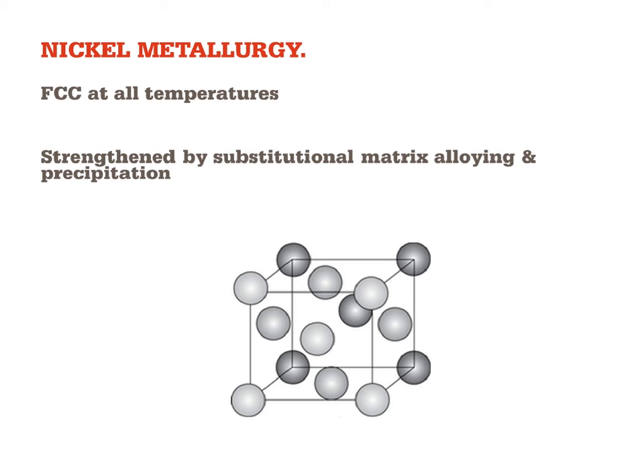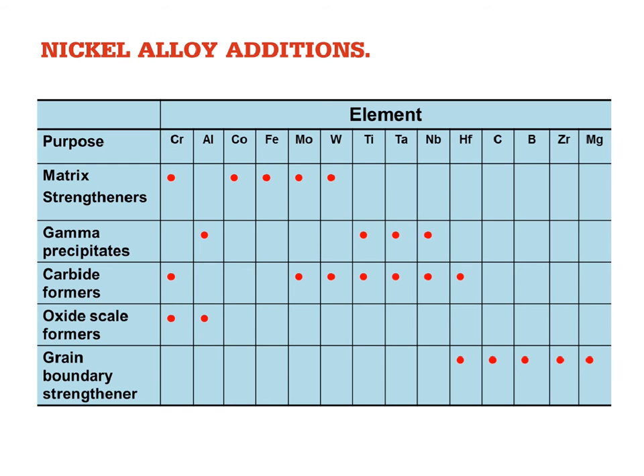But the main metallurgical feature of nickel alloys is a large number of different forms of precipitate. So growing very small volumes of precipitate materials, for example, using titanium, tantalum, niobium. We can grow carbides of chromium, molybdenum, hafnium, you can see here. And sometimes we want to grow precipitates on the grain boundaries to prevent them from moving, particularly for creep resistance. So things like boron and zirconium would be used for that.